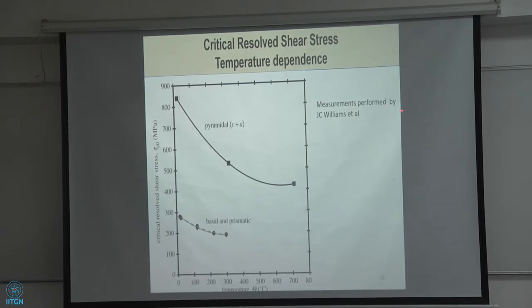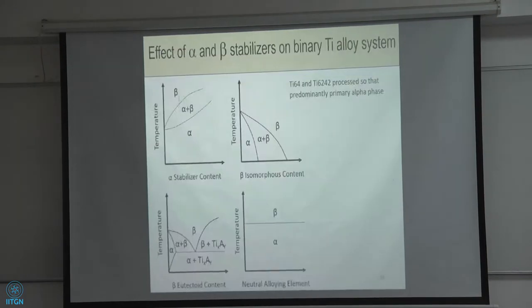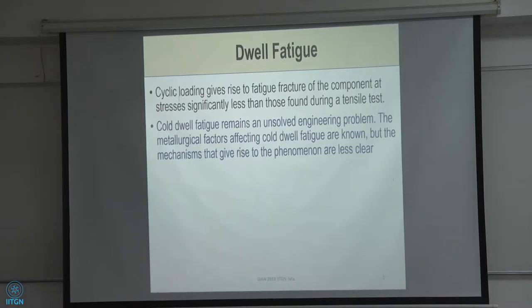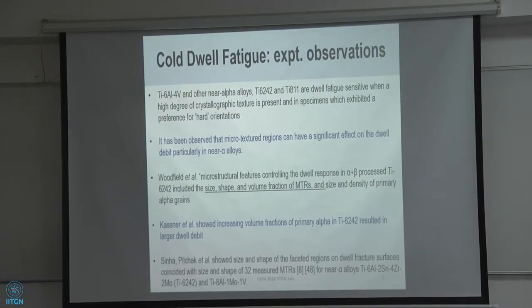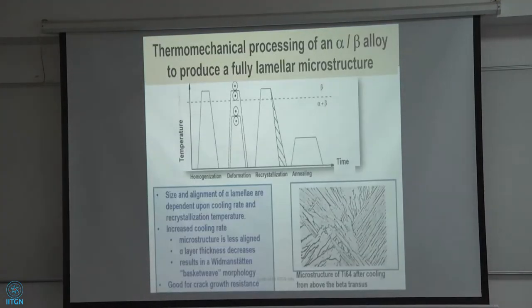So the plastic anisotropy in alpha-beta or alpha titanium alloys comes because of this phase, okay? Because if it's only FCC phase or BCC phase, it's very simple. FCC phase, we only have one dominant slip plane, 111. We have other slip planes too, but the 111 family of slip planes are for FCC. And for BCC, it's 110, okay? That's that. So the plastic anisotropy in near alpha titanium alloys comes because of this HCP crystal structure.